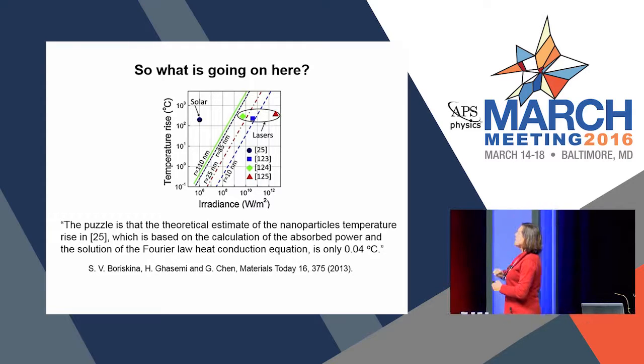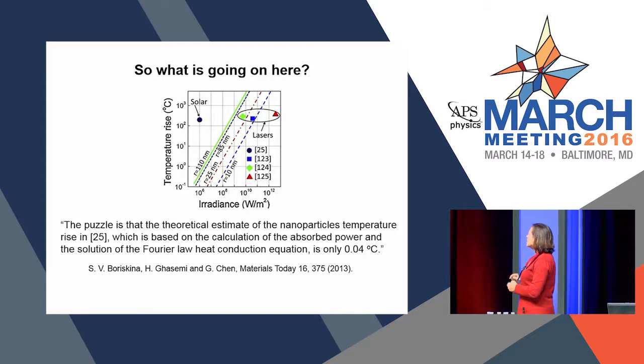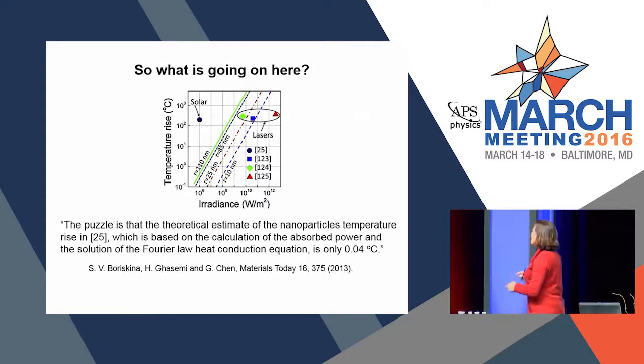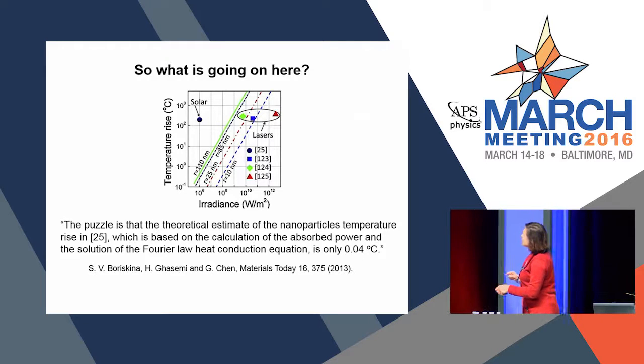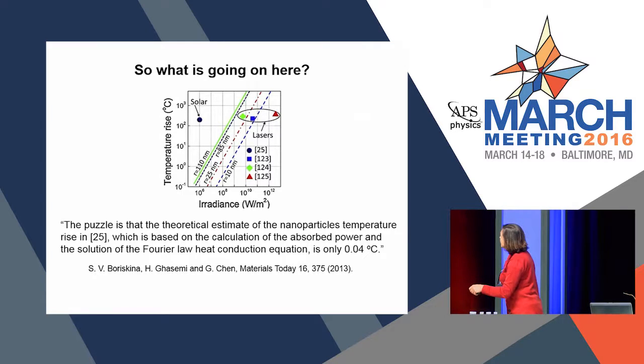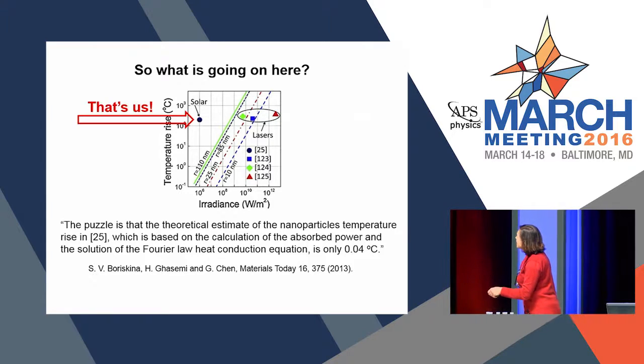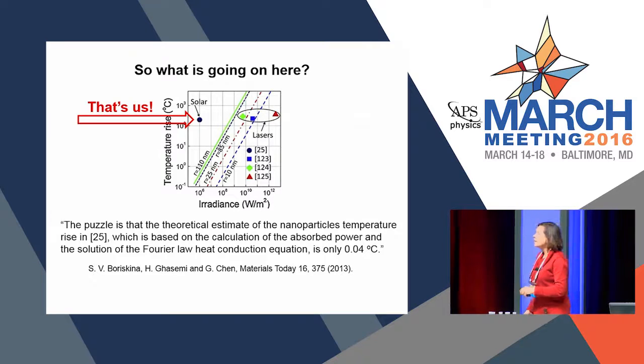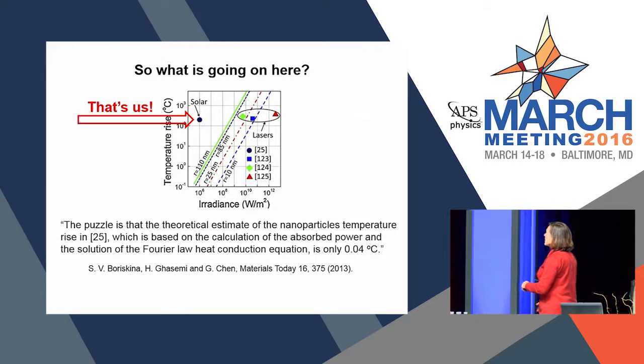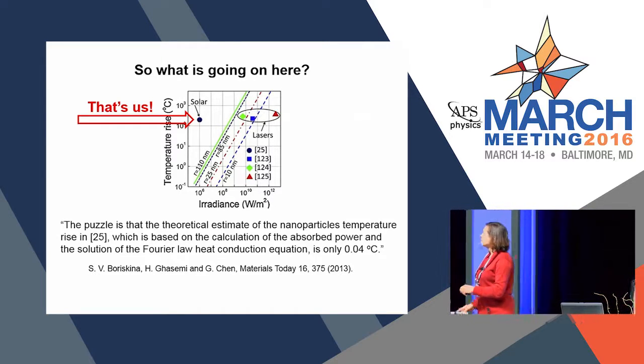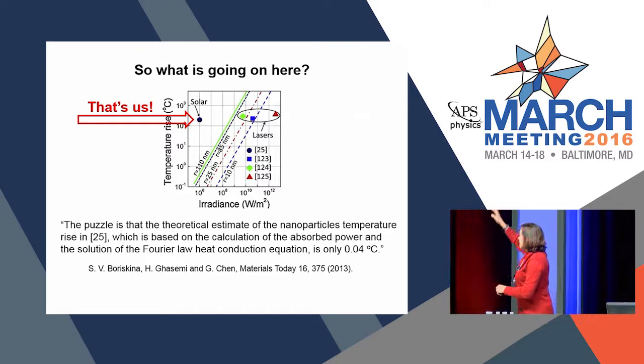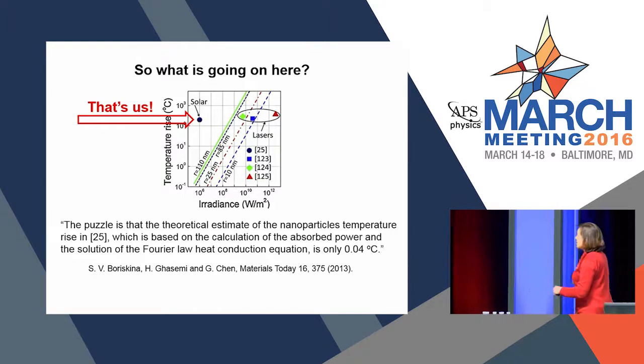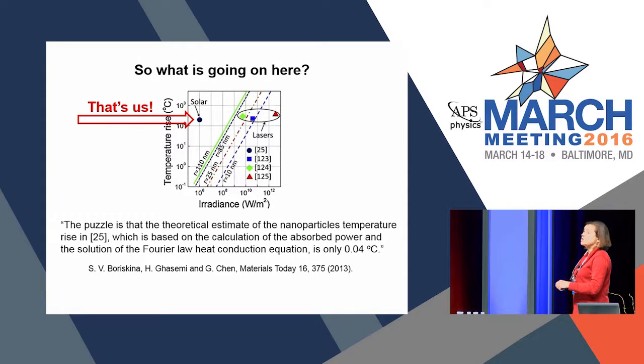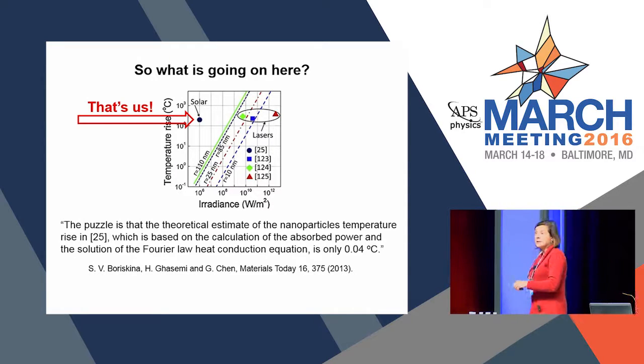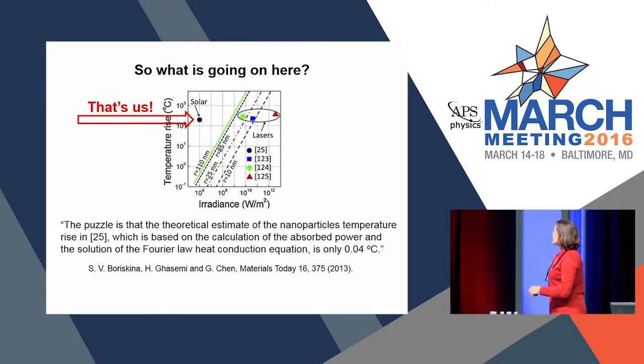So this beautiful review article was written right after our paper came out, where they looked at people who were doing laser experiments with bubbles and nanoparticles, and they all had data over here. And our data was over here, and they wrote this nice paragraph about us. The puzzle is that the theoretical estimate of the nanoparticle temperature rise in 25, that's our paper, which is based on the calculation of the absorbed power and the solution of the Fourier law heat conduction equation, is only 0.04 degrees Celsius. So we agreed there.